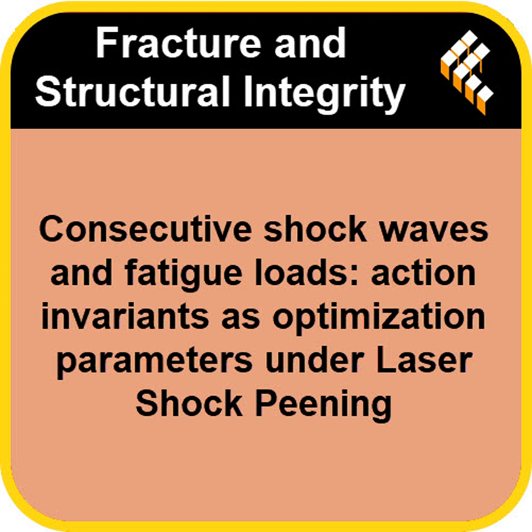That can't be a coincidence. What does it imply? It strongly suggests that the underlying physics, the collective behavior of defects, is analogous in both scenarios. Think about the tiny process zone right at the tip of a growing fatigue crack. The way defects organize and dissipate energy there seems to follow similar scaling rules as the defects organizing within the high-speed plastic shock wave front, like those shear bands we mentioned. So the universe uses the same math rule for breaking things quickly and breaking things slowly. It seems that way, at least in terms of this energy dissipation scaling.